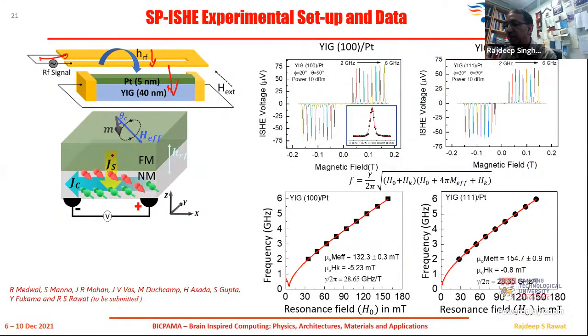And therefore it will make the spin precess in the ferromagnetic layer. Because of that, there is a current J as the spin pump. It's a pure spin current that is pumped to the neighboring non-magnetic Pt layer. When this spin current is pumped to the non-magnetic layer, it will produce a charge current because of the inverse spin Hall effect. So there is a charge current that will now flow in this non-magnetic layer. Because of that, there is a voltage that will develop across it. And this is the voltage which we call V_ISHE.